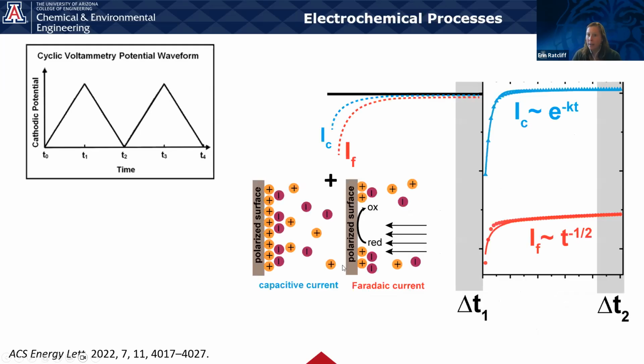Well, in an electrolyte, we have a high concentration of ions that are there to establish the electric fields. But when we apply a potential with time, this acts like a capacitor. And so those ions start to move around, back and forth, like double layer behavior on a metal electrode. This causes a current, a charging current or a discharging current. The challenge with a low defect density is that that Faradaic current is much smaller, and so it sits on top of a high capacitive background.